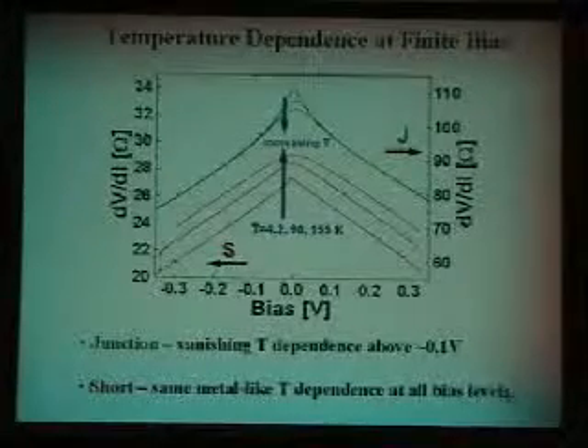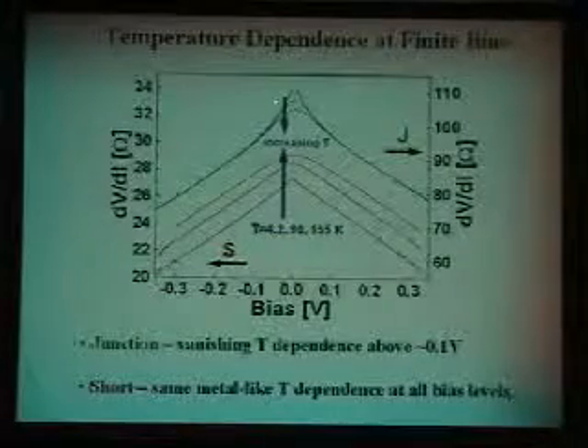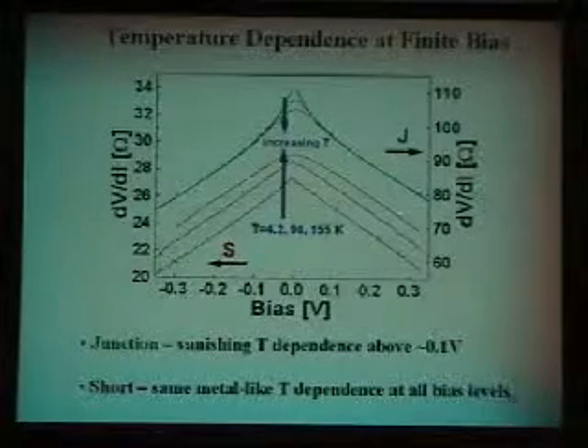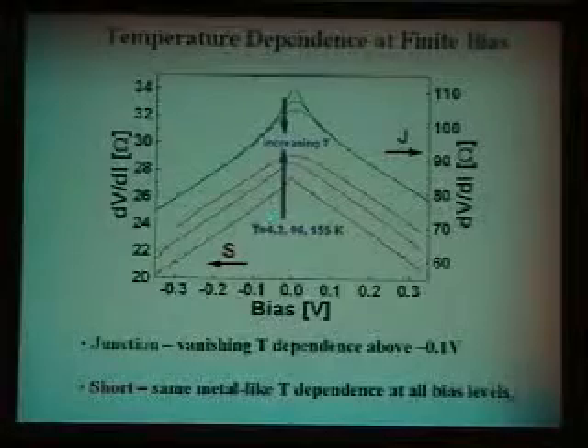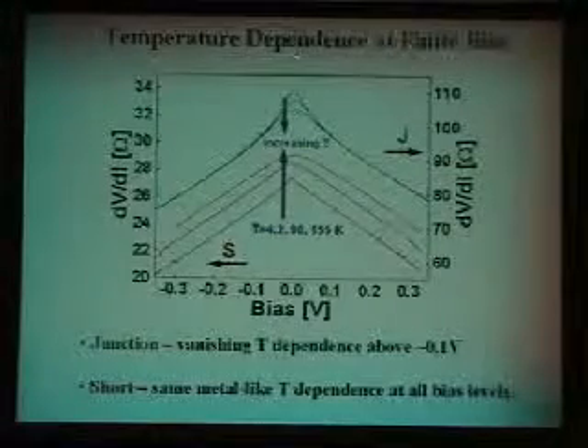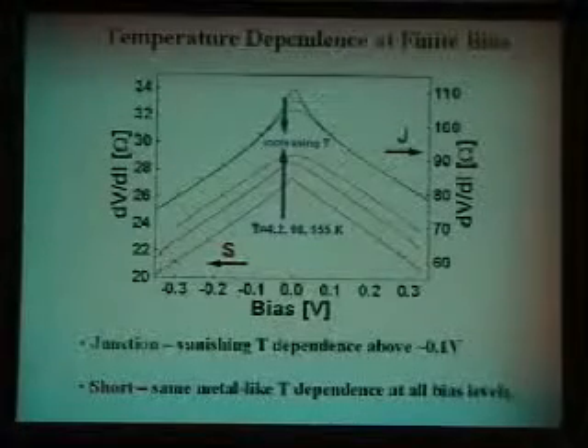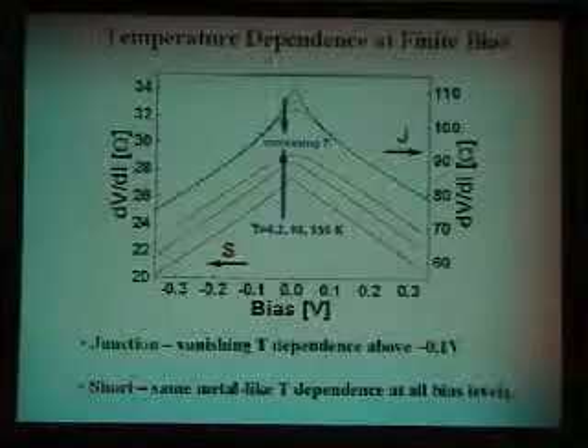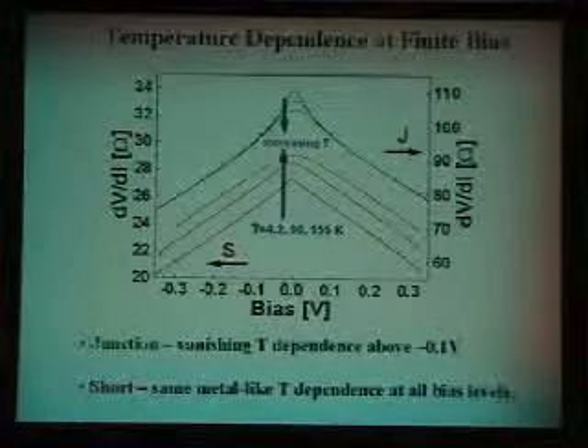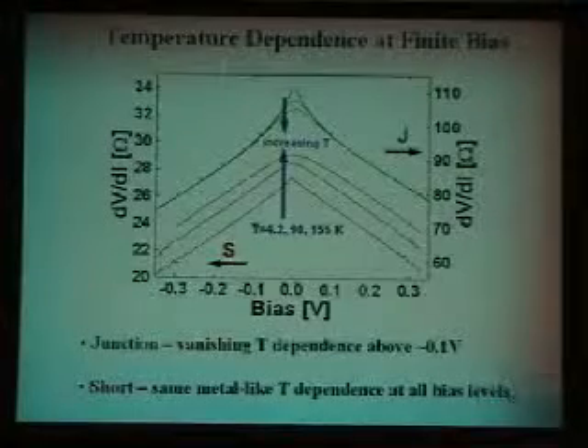Okay? And now comes the question about the temperature dependency. Here is where the thing is. If you take the junction and you measure its temperature dependency, there is the dV/dI, and there is the dV/dI for the short. And notice that the very first thing you notice in the temperature dependence is that at zero bias, it goes down as you increase the temperature. Here, it goes up as you increase the temperature. And there's very little temperature dependence here at finite bias. There's a lot of temperature dependence in the short at finite bias. And that's exactly what you'd expect again. And I'll show you in a second why.